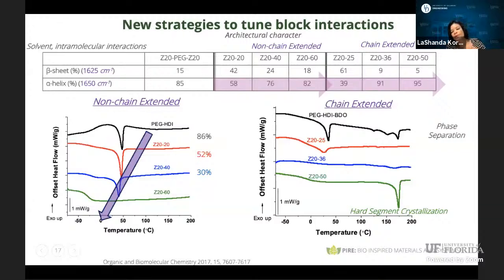And so one of the ways that we wanted to explore that is using differential scanning calorimetry, shown here at the bottom. These are all exotherms up. If we look first at the non-chain extended systems, for the PEG HDI, which is our control non-chain extended polyurea, you see a PEG melting transition, 86% crystallinity. For your Z20-20, you now have a reduction. You still see the PEG melting transition, but a reduction to about 52% crystallinity. You see a slight shift for the Z20-40 to a lower melting transition, and then you also see a lowering in that crystallization behavior.